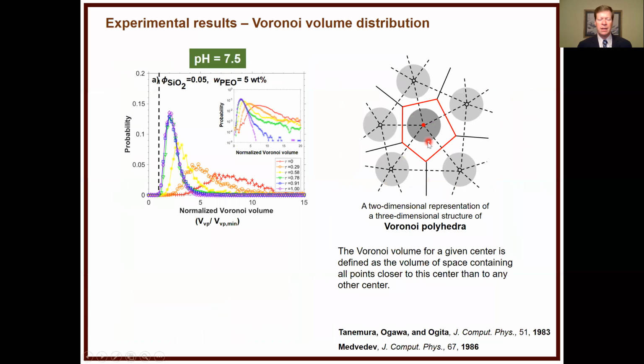And so what we can do with the Voronoi polyhedra is essentially draw a line between the centers of each particle, and at the mid-plane of that line, draw up this plane, and then you can reproduce this for all neighboring particles. In this case, we're just doing it in 2D, but you can imagine in 3D, if it's a perfect crystal, it'd have 12 nearest neighbors, and it'd have a polygon that's characteristic of an FCC crystal.